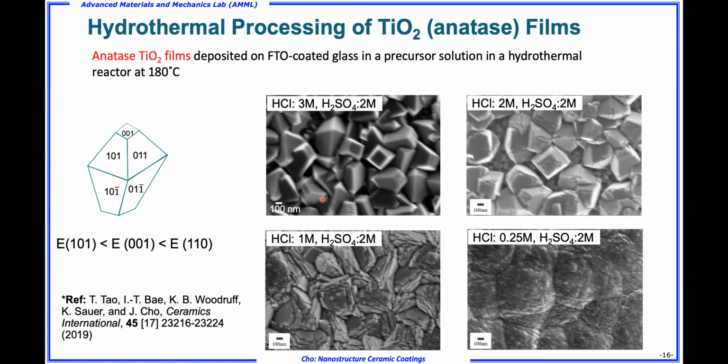So when the supersaturation is really low, you can see this equilibrium shape, very consistent with the drawing. But as the supersaturation increases, the equilibrium shape is a little bit distorted. And then here it's almost impossible to identify the equilibrium shape. Especially at high enough supersaturation, you begin to see more of a particle structure, generating this domain structure. So each domain consists of smaller nanocrystallites.